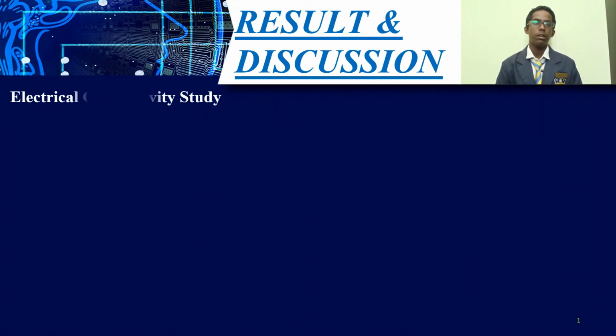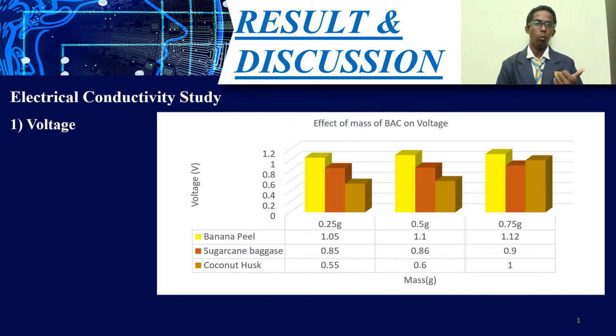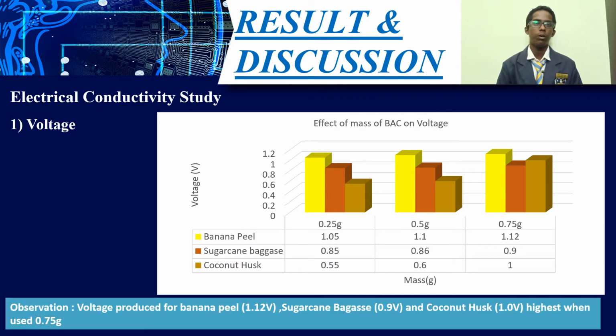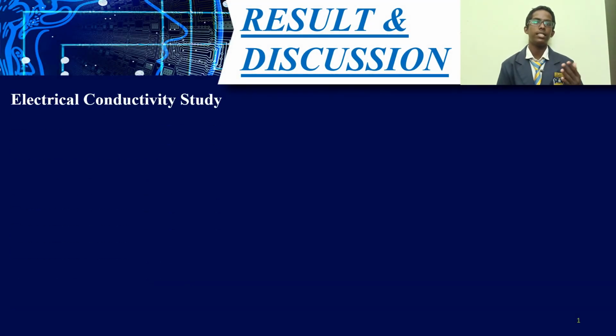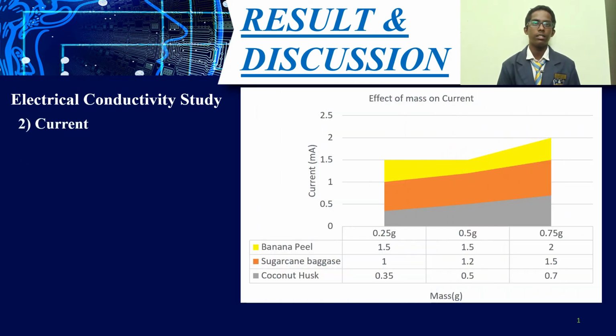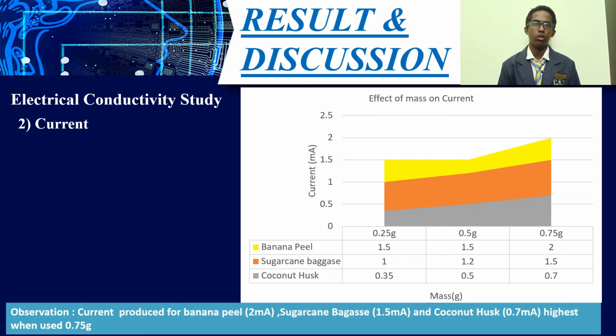We have also done 3 types of electrical conductivity tests, which are voltage, current, and polarization and power density curve. In the voltage against mass graph, we can see that when 0.75 gram of BAC powder is used, the voltage produced is highest, which are 1.12 volts for banana peel, 0.9 volts for sugarcane bagasse and 1.0 volts for coconut husk. Based on the current against mass graph, we can see that the current produced is the highest, which is 2 mA for banana peel, 1.5 mA for sugarcane bagasse and 0.7 mA for coconut husk.